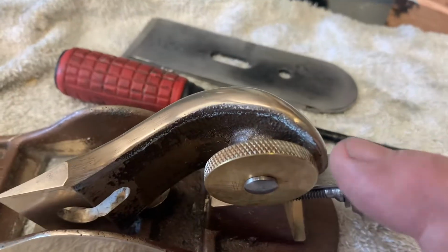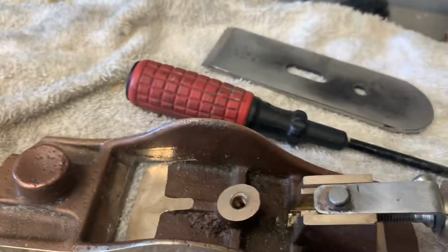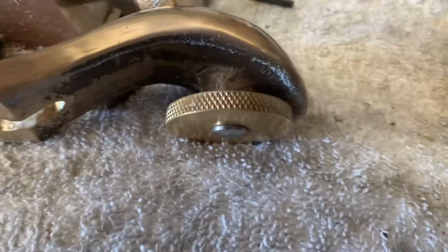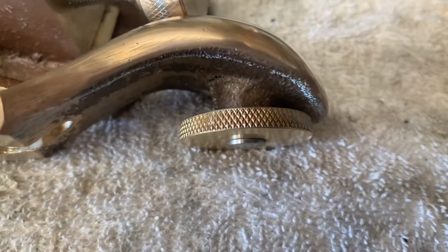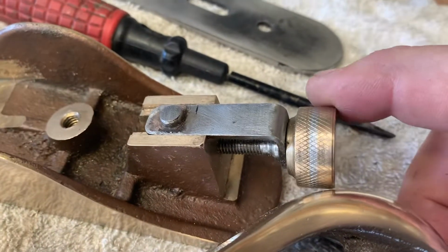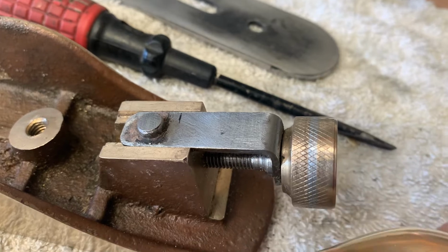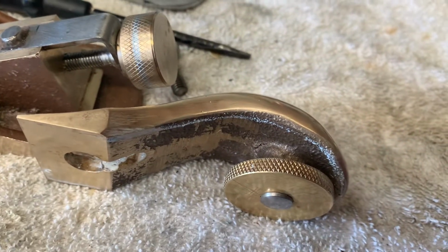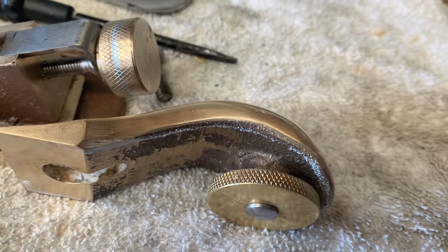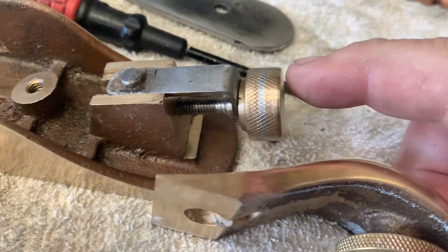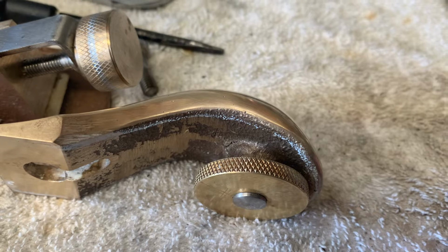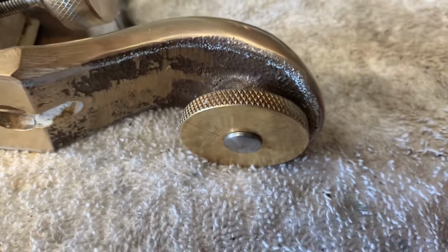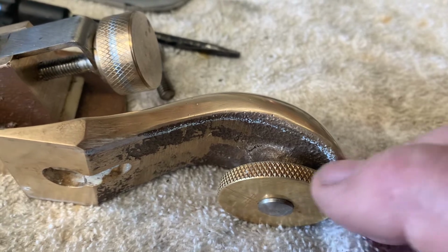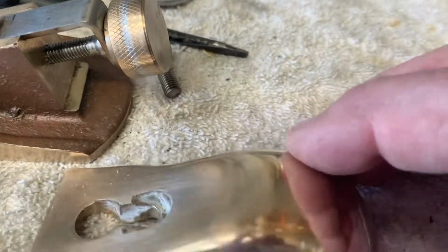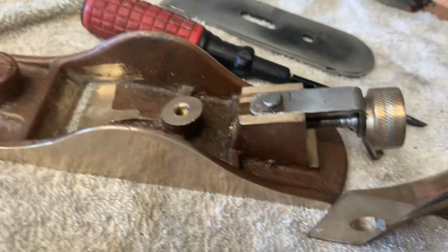This part here is made out of brass. And I've made that out of brass for a simple reason: I want to be able to knurl it. And the aluminium bronze is just, you can see where I've tried to knurl that, it's just a bit too hard, because when you're knurling it, you're actually pushing the metal out, you don't cut it in. The aluminium bronze is just a little bit too hard, and as you can see, it doesn't go well. So I had to get some old taps and plumbing fittings, and I've melted them down and re-poured it and machined those up there. And this bottom bit there, that's made out of 316 stainless.